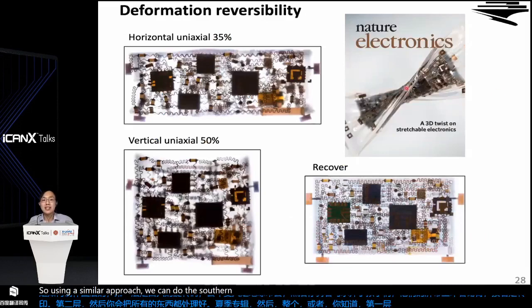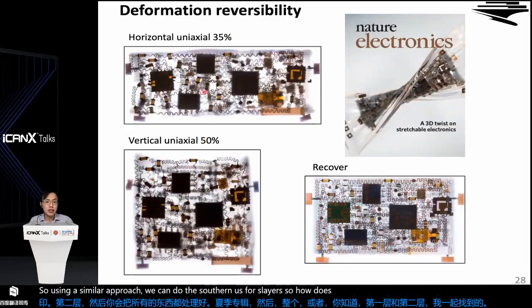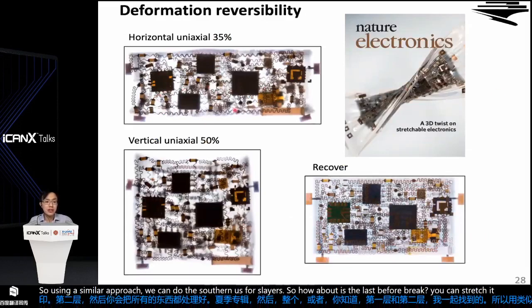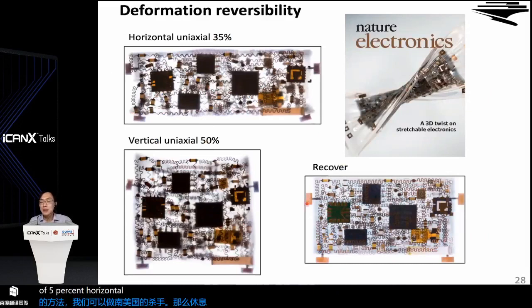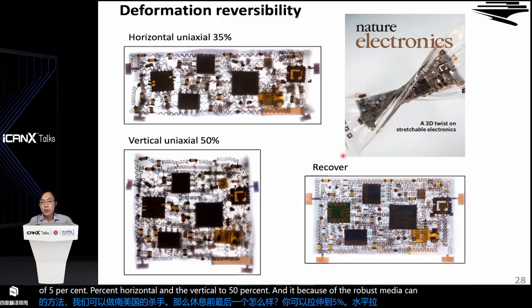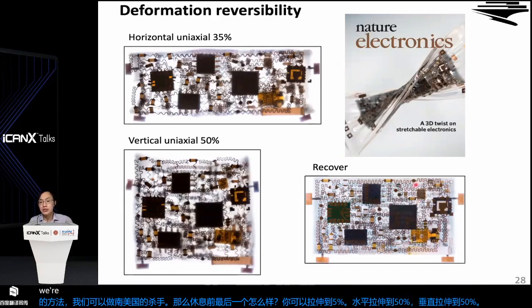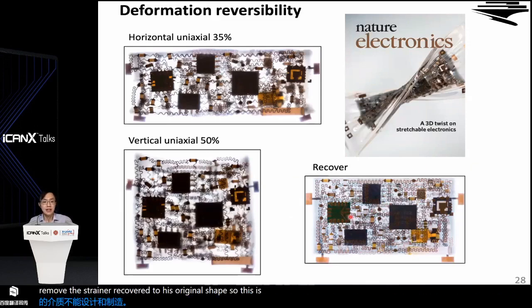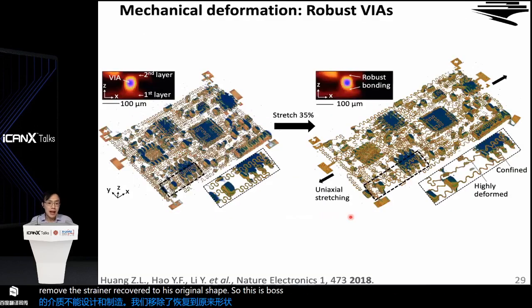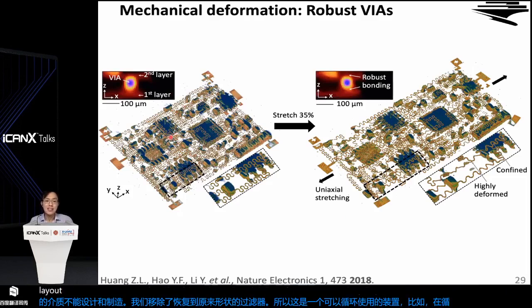So how does this device deform, right? You can stretch it to 35% horizontally and vertically 50%. And because of the robust mechanical design and fabrication, we remove the strain and it recovers to its original shape, right? So this device can be cycled over 1,000 cycles. And how does each layer of this device deform? And this, as I said, was the first demonstration of this multi-layered stretchable device in the literature.